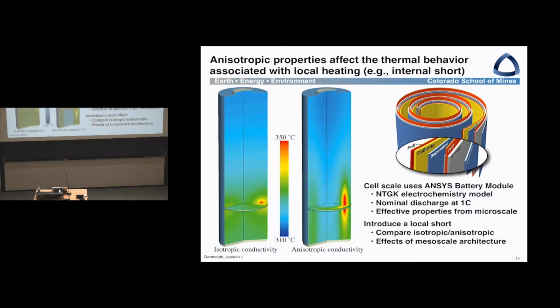So when we look here, again, I've taken a battery and just arbitrarily produced a short. In other words, a local hotspot in that battery. And so what you see here is that compared to assuming isotropic properties, in fact, they're anisotropic properties, and because of the role of the current collector foils, you preferentially transport the heat axially and less so radially. And that has a big effect on the time it takes to come to a thermal runaway or some other accident event upon an internal short.